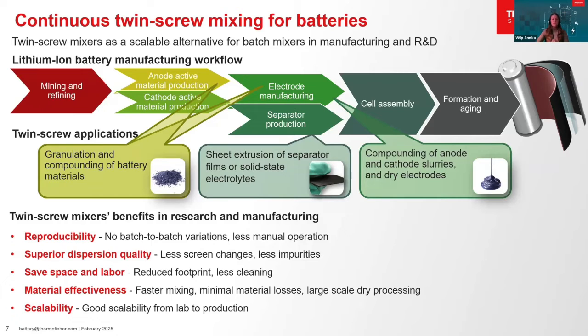For electrode manufacturing, twin screw mixers enable the continuous mixing of cathode or anode slurries, and this offers a beneficial alternative to batch mode mixing, typically done with planetary mixers. In manufacturing, the twin screw mixers provide the following benefits over planetary mixers. The reproducibility is better. Twin screw mixers ensure there are no batch-to-batch variations, enhancing the consistency of the production process. There's less need for manual operation, reducing the impact of the individual operator handling.